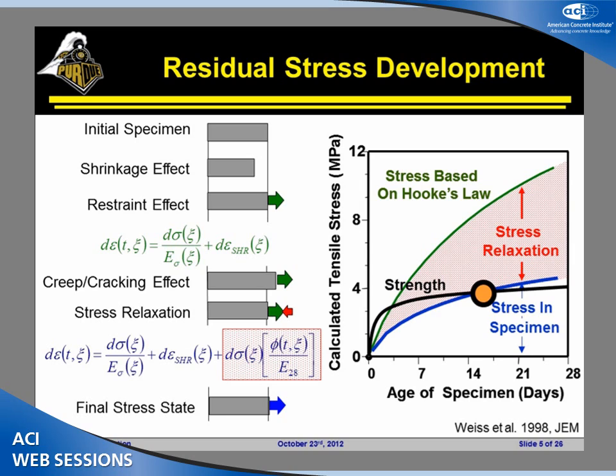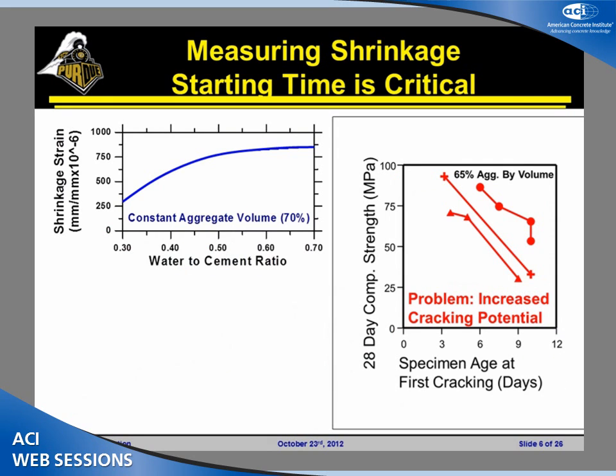In addition, the higher performance concretes tend to be more brittle, right? But you may say, well, but I'm going to make it up because when I look at this, I'm going to have lower shrinkage in the overall system, right? So you can go to a textbook and you can say, well, if I look at the shrinkage, it decreases as a function of water to cement ratio. But what I'm going to point out is when we look at restrained shrinkage cracking data, we have the age of cracking here plotted against the 28-day strength. The higher the strength, typically the more susceptible the concrete is going to be to cracking. Now you may say, well, why is this if we're decreasing the shrinkage?